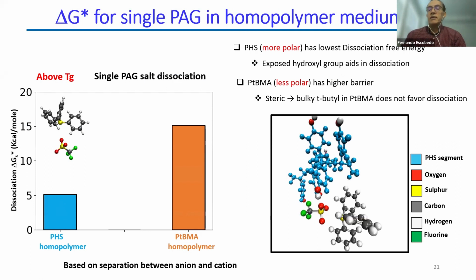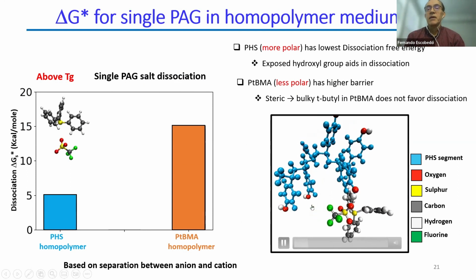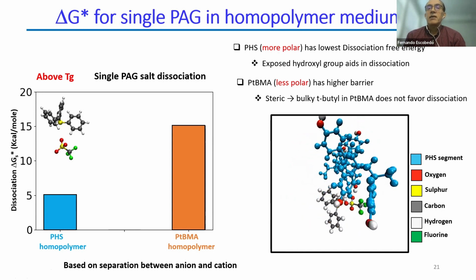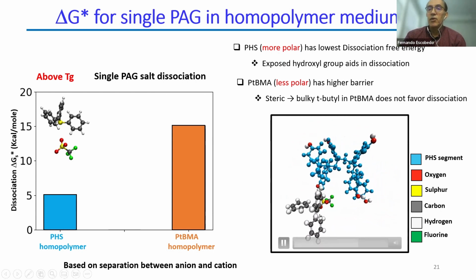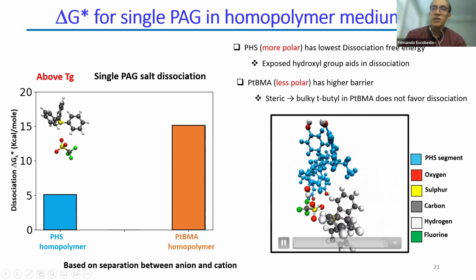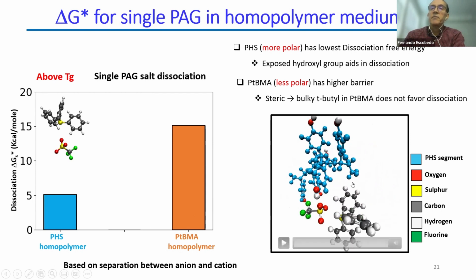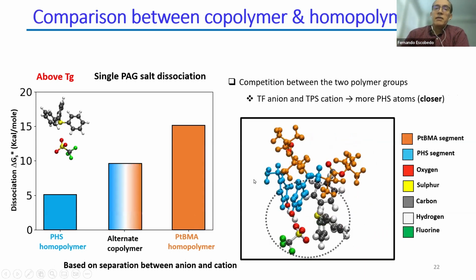But you can also, of course, look at the molecular structures of these systems and realize that, for example, in PHS, both the anion and the cation, which are shown below here, interact more closely with the polar groups, the OH in PHS. Even though PTBMA also has a polar group, the CO, the carbonyl group, because of the bulky tert-butyl group, it's more hidden. So there's steric hindrance, and hence it's not as effective at interacting with and dissolving the ions. And if you look at the alternate copolymer, you see behavior in between, so the barrier to dissociation will be intermediate between the two.